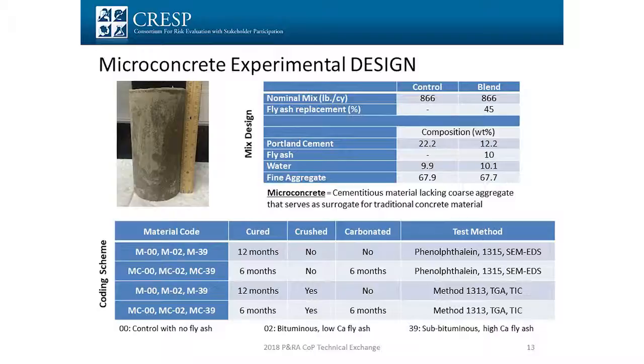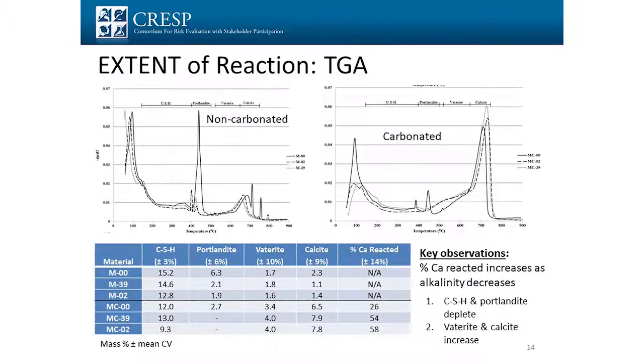So this is basically looking at how fly ash replacement, with 45% of the Portland Cement being replaced by fly ash of various alkalinities, would affect the carbonation and the oxidation of the material. These things were all aged initially for 6 months, and then carbonated or oxidized or put in an oxygen environment. So we did carbonation only, oxidation only, and carbonation and oxidation combined as this series of studies. I'm just touching on a little of them, but this is all in her dissertation. We also looked at the alkalinity of the fly ash itself. As you can see, there are some significant effects.